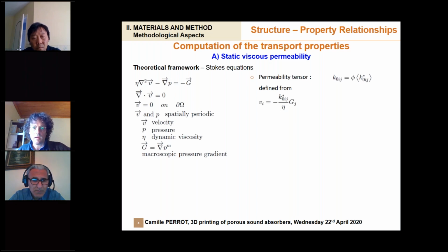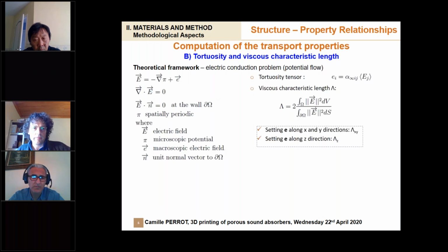This is an important parameter for acousticians, which is basically the reverse of the resistivity times the viscosity of air. Another fundamental transport phenomenon we get at the opposite, high frequency range is the dynamics of the fluid when the fluid is non-viscous, when there are no viscous exchanges between the solid frame and the fluid phase. And then all the physics is governed by potential flow equations, which is formally identical with electric conduction problem.